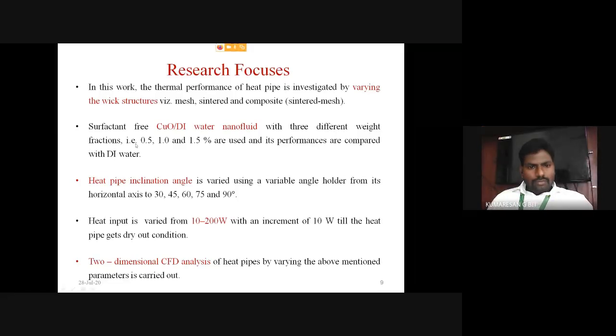I studied the following parameters to analyze the performance of the heat pipe. In this work, the thermal performance of the heat pipe is investigated by varying the wick structures like mesh, sintered, and composite, that's the combination of sintered and mesh wick structure. Then, in addition to varying the wick structure, surfactant-free copper oxide nanofluid with three different combinations, 0.5, 1, and 1.5 weight fraction, is used, and its performance is compared with its base fluid. Then orientation is varied from 0 degree to 90 degree in steps of 15 degrees.